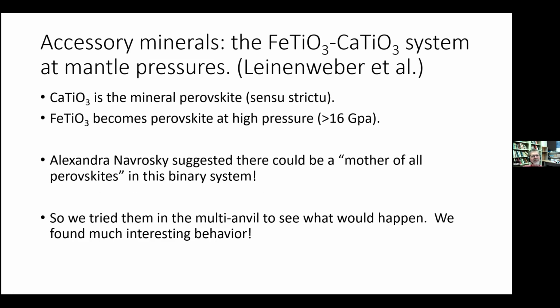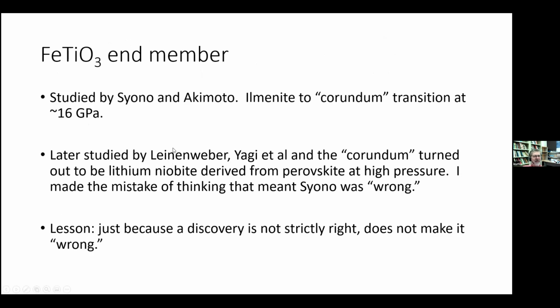So we did that, and we didn't find a solid solution like we were thinking. Now that I think about it, the sizes are quite different. We found ordered phases in between. So as far as the FeTiO3 end member, it was Syono that called it a corundum, and it turned out to be lithium niobate. They look very similar in X-ray. And I now realize Syono discovered this material. We were back then, in that sort of thing of, it was one of my first studies.